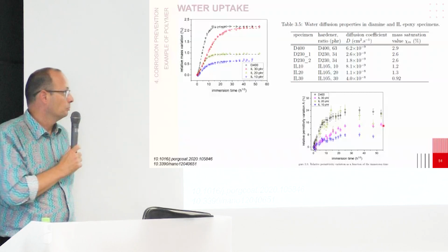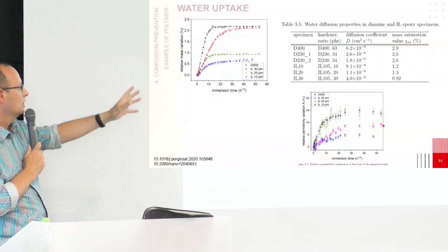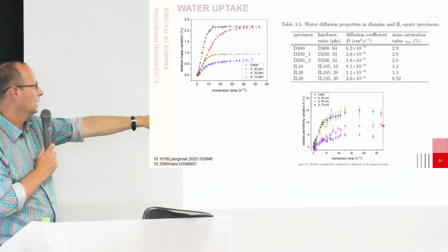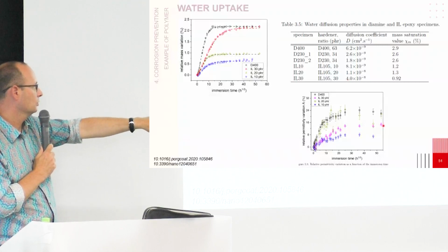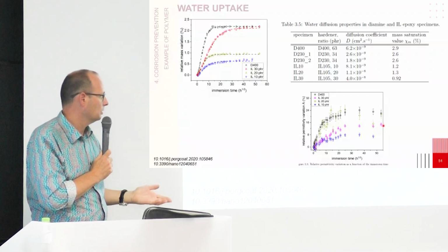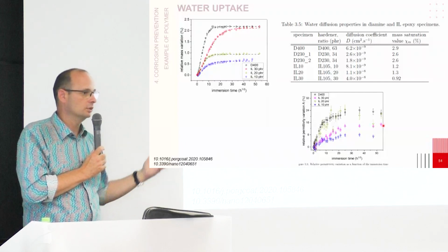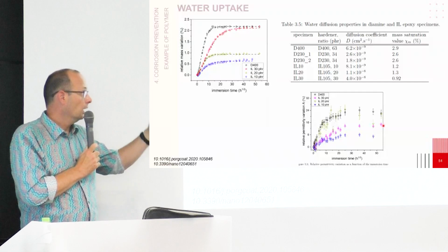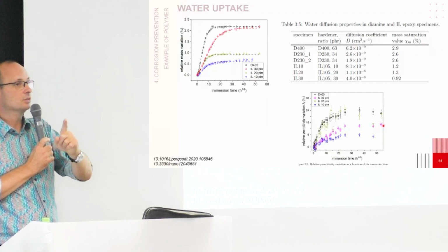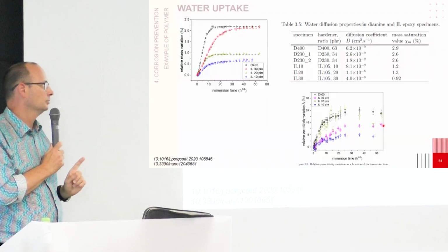Of course, you could apply the same method to capacitive measurement, and here the idea is to say, okay, I know that I can rely on capacitive measurement, so I can use the permittivity of the material as a function of time as a parameter to follow any evolution of water content in the material. And saying that, I can choose a right non-destructive technique to evaluate these properties when I'm on site.